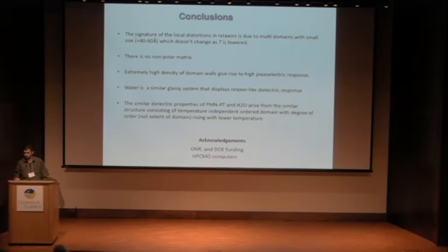Regarding the glass-forming liquid, even if you apply a field, polarization never appears. And also, in glass-forming liquid, there is no first-order Raman scattering. However, in PMN above TC, strong first-order scattering appears by the symmetry breaking. There's no polarization appearing in the hydrogen bonded system.